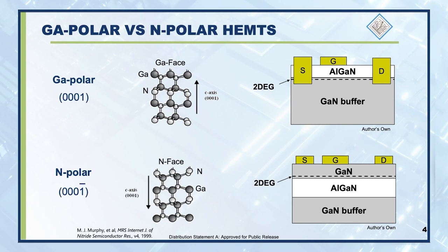So I've talked about gallium polar GaN and nitrogen polar GaN. What does each of these materials look like? Gallium polar GaN, if you look down on the crystal face, what you'll see is just gallium atoms. Nitrogen polar GaN, if you look down on the face of the crystal, you'll see nitrogen atoms. And they are stacked in this hexagonal close-packed structure, which is typical of the crystal of gallium nitride. So literally, nitrogen polar GaN is traditional gallium polar GaN flipped on its head.